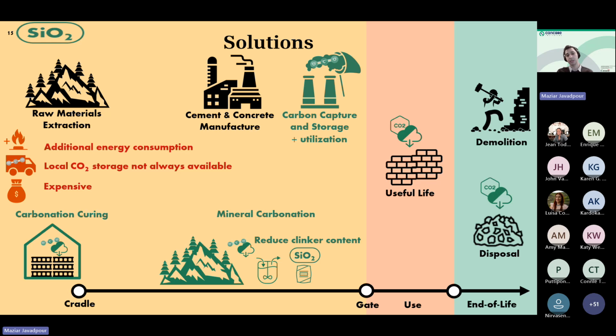So the scientists look at the concrete life cycle chain, and they saw that concrete has this remarkable ability to absorb CO2 from the atmosphere during its useful life and end of life. So they thought, well, what if we put all that concrete in this chamber and then we expose it to concentrated CO2, which will react to the cement and gets permanently locked into concrete, right? And it might or may not, depending on how we do it, actually improve concrete properties.